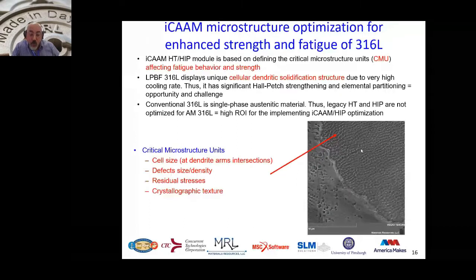From the post-processing level, this material is very unique, and instead of going with the conventional heat treatment approach, we have developed at MRL, through another funding from NAVAIR, an optimized heat treatment for this alloy that allows us to provide properties that exceed the performance of wrought alloys. So you can see we control the cellular structures, and we have to look at the residual stresses and the crystallographic orientations. And when we implemented this heat treatment, we're able to optimize the behavior of the alloy, and that's what you will see in the results in the next few slides.